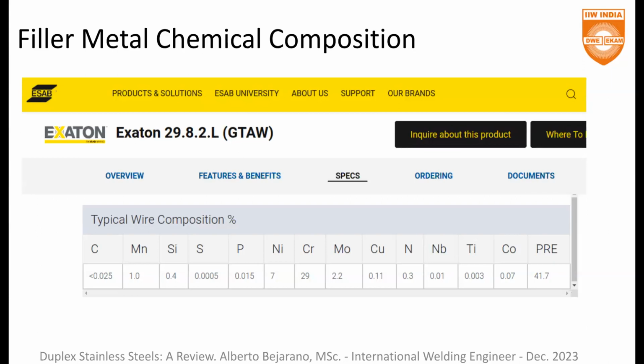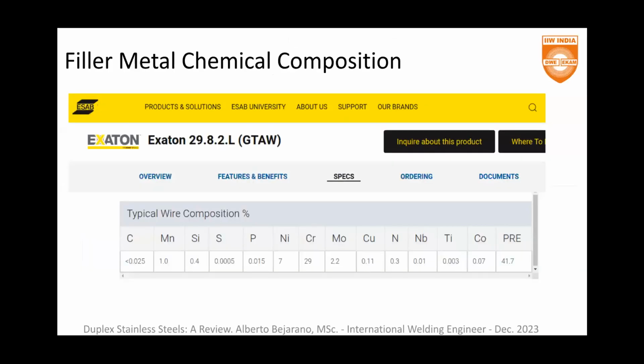To calculate the corrosion resistance of the weld metal, we have to measure the chemical composition in order to obtain a value. And as we will see in a moment, at the end of the welding process we can obtain 3 different values. One value for the base metal, one value for the heat affected zone, and a third value in the weld metal, which is very important, very important.